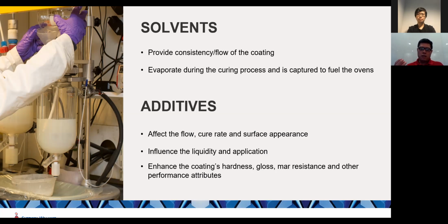And for coil coating and extrusion coating, most of this organic solvent will be captured and also burned to use as a heating source for the oven. So this aspect of the factory applied finish means that it does not emit any harmful toxin or off gases into the atmosphere as a result. Okay. When the solvent evaporates, the resin binds the pigment and color and additive to form the film.